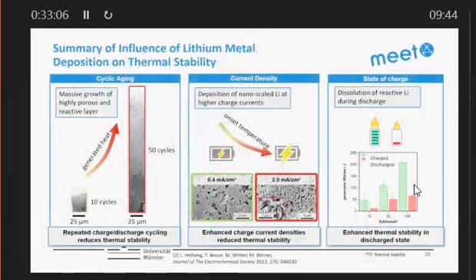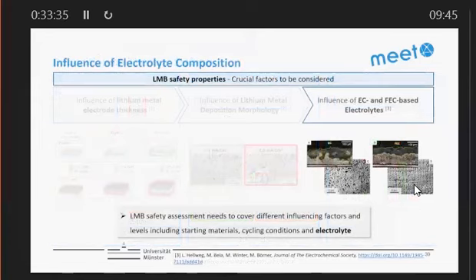So this is a summary here, on the DSC measurements, in addition to the little tips for making reproducible DSC measurements. I basically have shown that with cycle number, current density, and also the state of charge, which is the charge state, you have a more unsafe situation. So proven as it is, but I think the extent is something which at least some of us maybe find interesting to know. Finally, electrolyte composition.